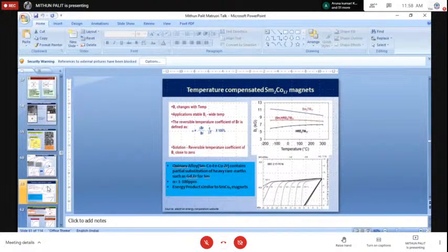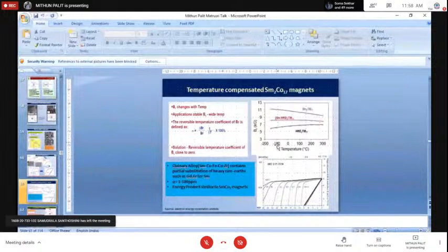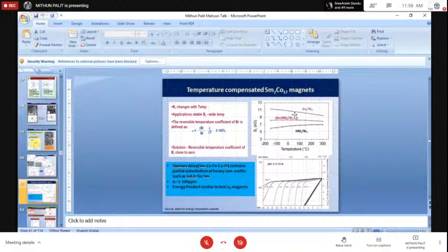In the 217 type of material, we also have another grade of 217, which is called temperature compensated 217. Normally, if we take any permanent magnet material and slowly increase the temperature, its magnetization, that is the remanence, continuously decreases. However, there are some special grades of Sm2Co17 class of magnet where the magnetic flux can be kept constant at least for a range of temperature. The cartoon in the top right corner shows the nature of the different rare earths, R2 transition metal 17, where R stands for rare earth. In some of the compounds, you can see the blue curve on top, the magnetization decreases with temperature. This is the case of Sm2Co17.